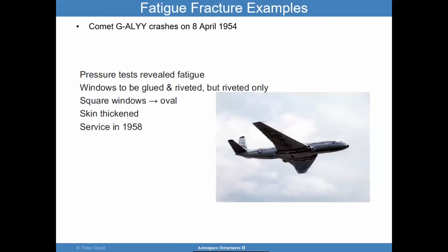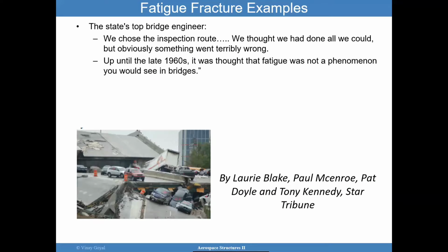The Comet G-ALYY crashed in April 1954. Pressure tests had revealed fatigue. And one of the issues is that they were using square windows, and so that was one reason why we had to go oval. There's also the situation of thickening the skin, so that's one of the things that had to be done.